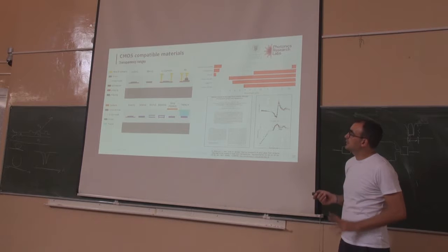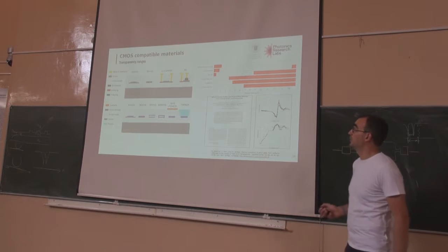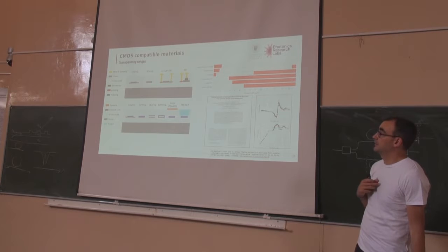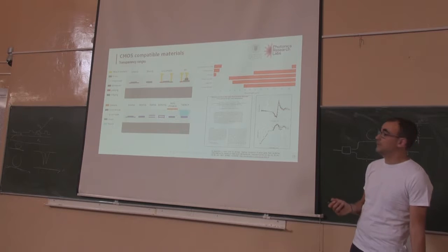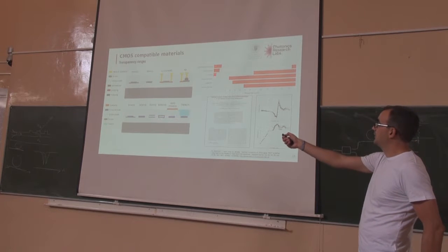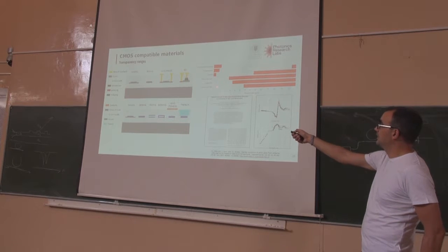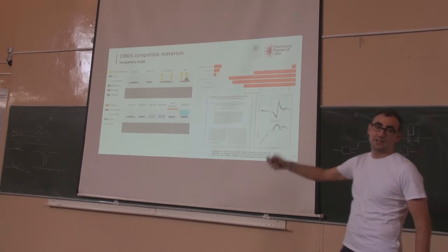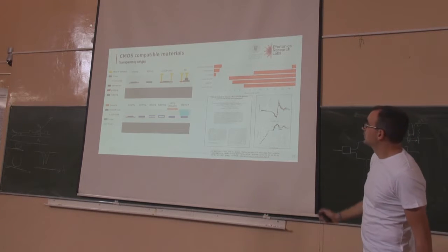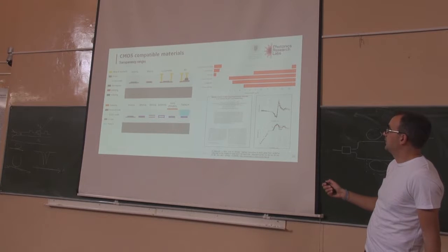So, the technologies that we have available as generic technologies and multi-project wafers, which we discussed in the introductory talk, use materials which are transparent in the mid-infrared. Okay, here you have the different materials and the wavelength, and this light shaded rectangle is transparent. This orange rectangle means it is not transparent anymore. So you have germanium-tin alloy, but you have germanium and silicon. Germanium is transparent from 2 microns up to nearly 15 microns. Silicon from 1 up to, I would say, more or less 8, 9.